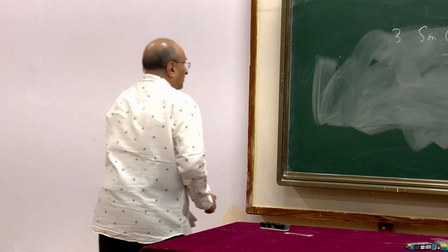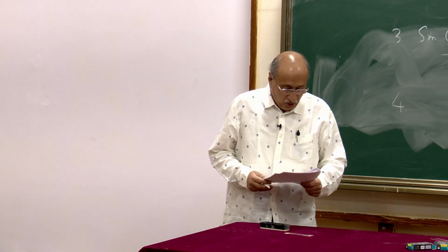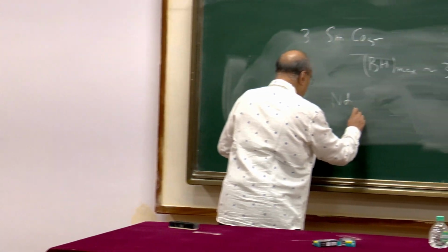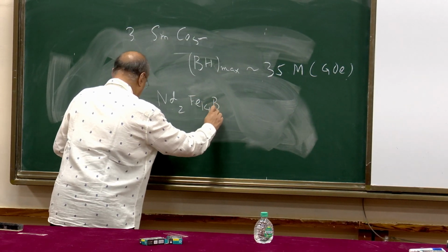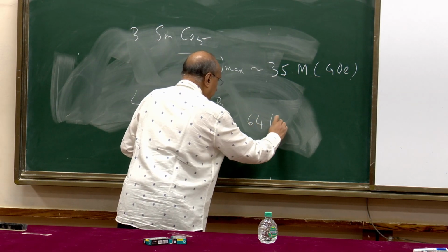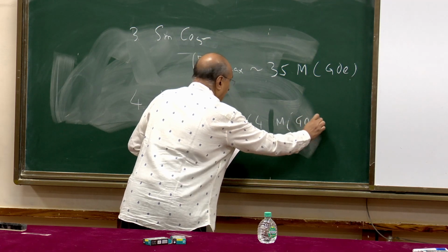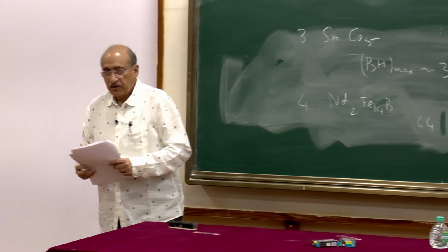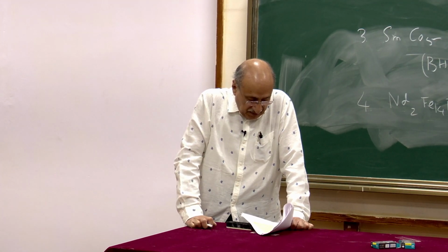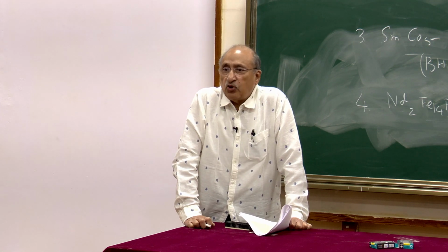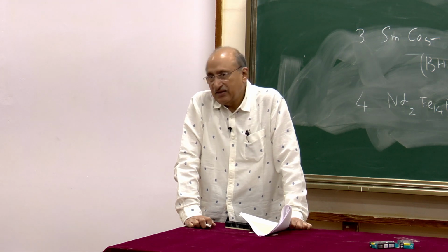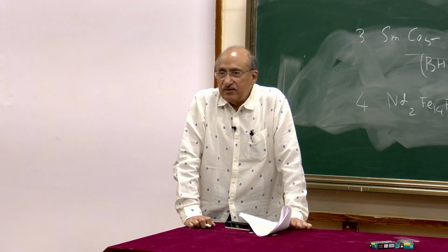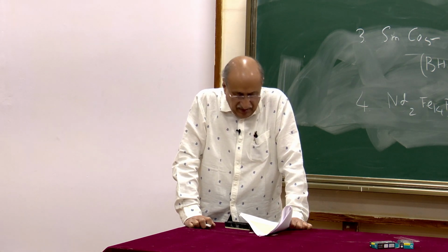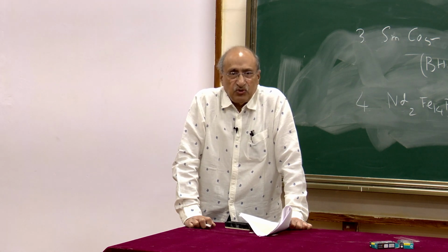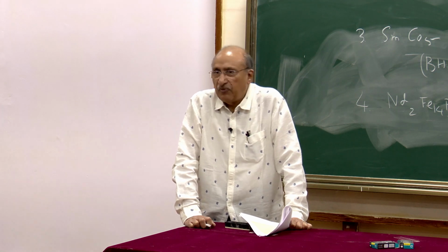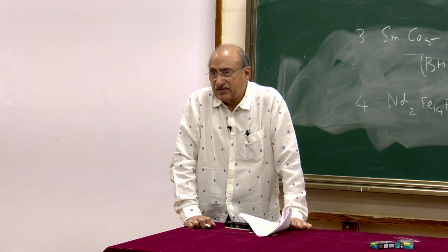But I know that for the 4th one, there is still a lot of work going on, which are neodymium iron boron magnets. Which has, this is 64. They are much cheaper in comparison to samarium cobalt. They have much better BH max. Sometimes people use nitriding to put some nitrogen to help TC, because the Curie temperature is also important. Problem here is the Curie temperature is somewhat smaller. So people tried to make TC better. There are many compositions which are being tried, as I mentioned to you. I know there are some people even in IIT Bombay who have been working on these type of magnets, neodymium iron boron magnets. Work is still going on on this particular magnet to enhance it and make it a better material.